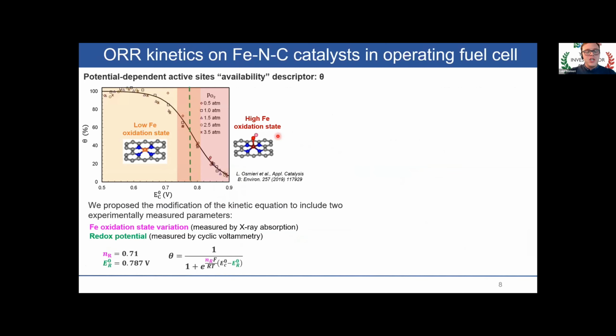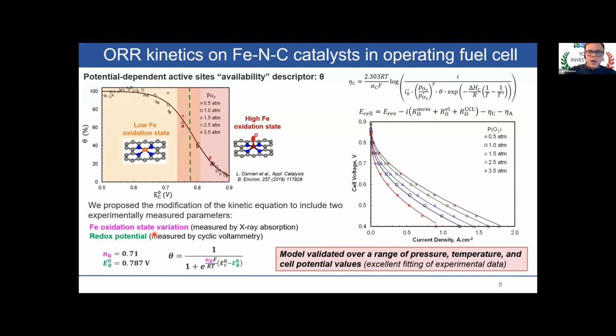So during the initial part of my postdoc at the National Renewable Energy Lab, I focused on determining the oxygen reduction kinetics on iron-nitrogen-carbon catalyst in an operating fuel cell electrode. Specifically, we proposed a modification of the kinetic equation to include two experimentally measured parameters, which are the iron oxidation state variation and the redox potential at which this variation happens.